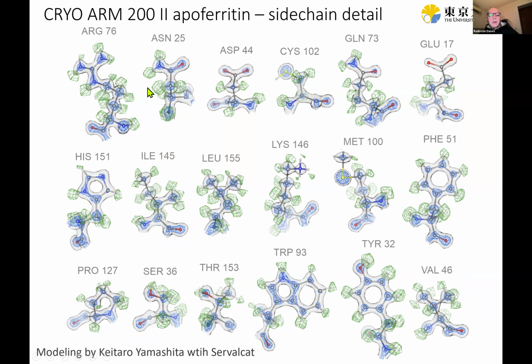And then by calculating a difference map between the hydrogen-omitted model simulated map and the experimental map, he created the difference map, which is shown in green. And at the normalized 3 sigma level, we can see putative densities for hydrogen atoms at most of the positions in the side chains that are shown here. So this is a very nice result also in terms of the identification and location of hydrogen densities.